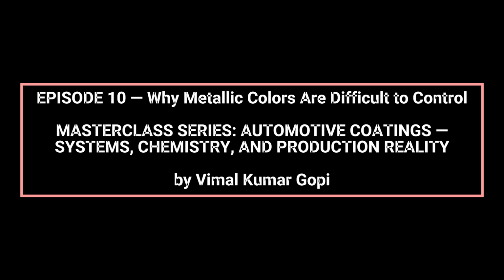During spray application, the base coat film initially exists in a highly mobile, solvent-rich state. In this phase, metallic flakes are influenced by gravity, surface tension gradients, shear relaxation, and convective flow. As solvent evaporates, viscosity increases, and these forces gradually freeze flake orientation into the final film structure. The challenge lies in controlling when and how this immobilization occurs.